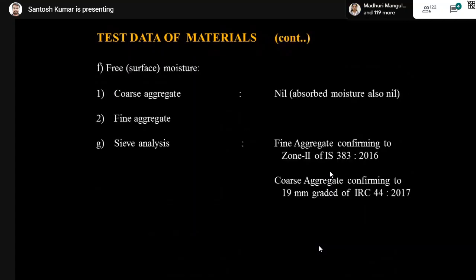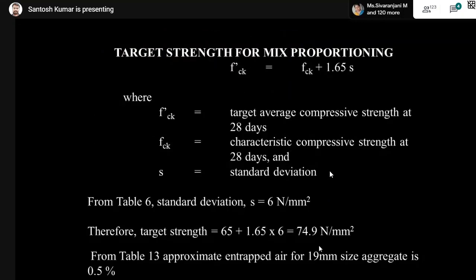So coming to the coarse aggregate, there is no surface moisture in this case. Fine aggregate, there is no surface moisture. Fine aggregate is conforming to zone 2, and coarse aggregate is conforming to graded size as per the 19 mm. See, the target mean strength for this M65 grade is 65 plus 1.65 into 6, and that is 74.9. In this case, the approximate entrapped air for 19 mm size is 0.5% as per table 13. So we are assuming the air content as 0.5%.